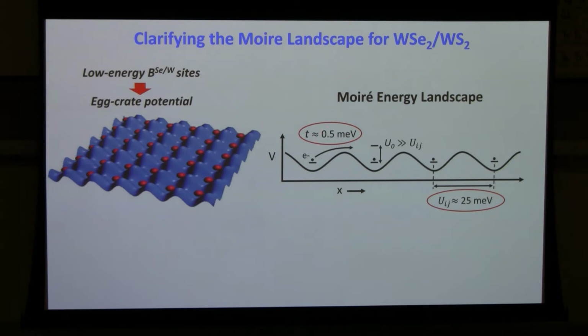So you can think of that as the kinetic energy per electron. And we're also able to figure out experimentally that this long-range Coulomb interaction of electrons on 2 adjacent lattice sites is 25 millielectronvolts. It's harder for us to measure this energy of double occupancy, but we are able to determine that it's bigger than this long-range one. So we think it's in the 50 to 100 millielectronvolt range.